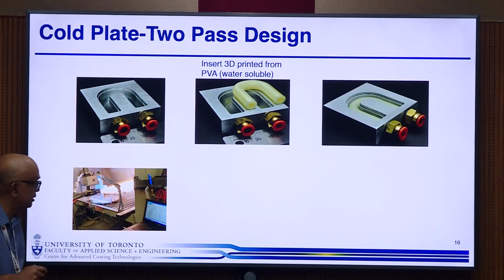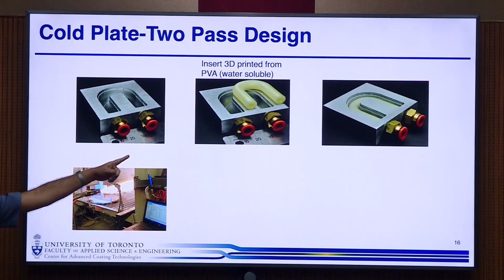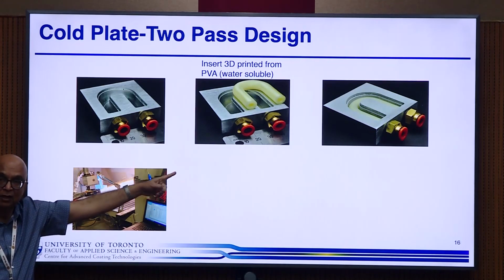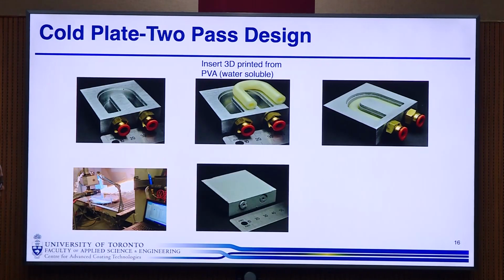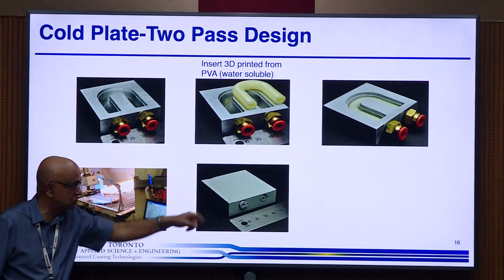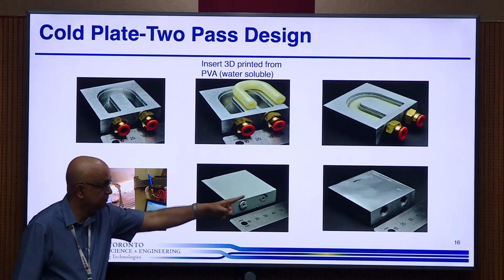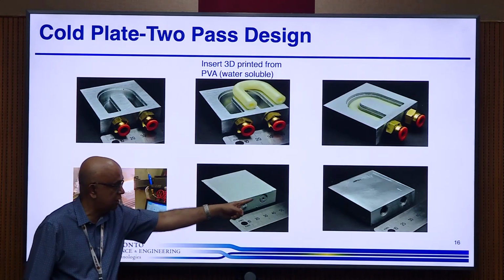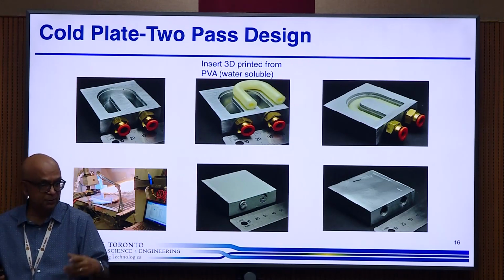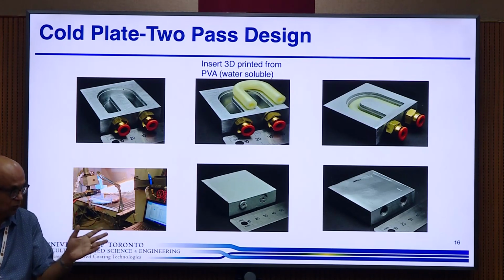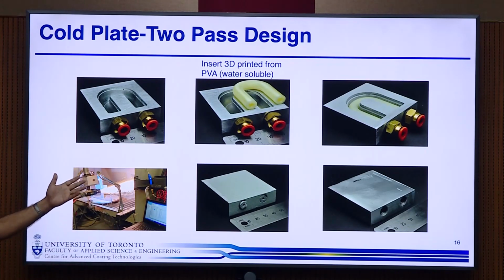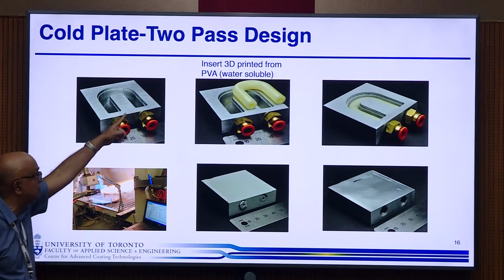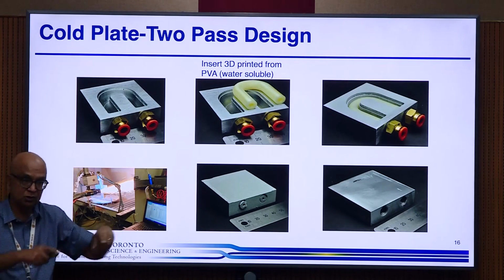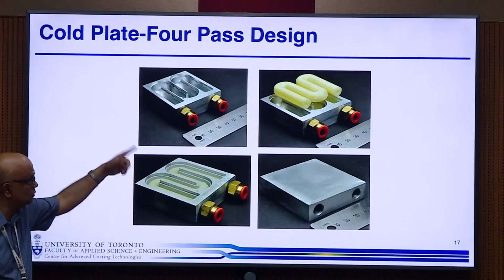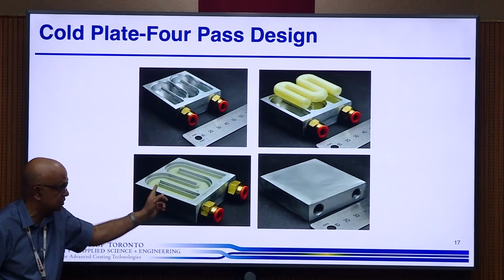We fit it inside, and then we spray metal over that entire surface, and we fill in that gap. So when you take it out, this is what it looks like. We machine the top, we put this in water, and we dissolve out that pipe. So now you just have a hollow inside. And we've got a heat sink. But now, of course, we are no longer limited by this radius. The original radius was because of the bending radius of that tube. So we can do something like this, and we can put 4 passes inside that.